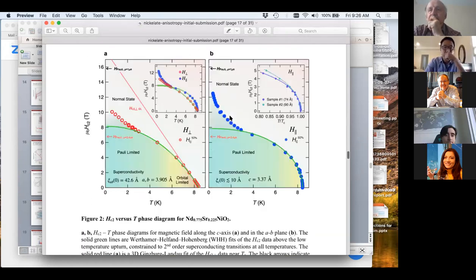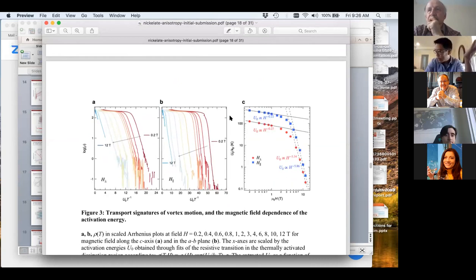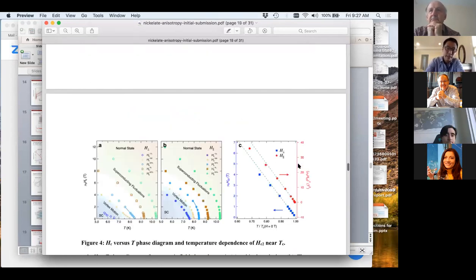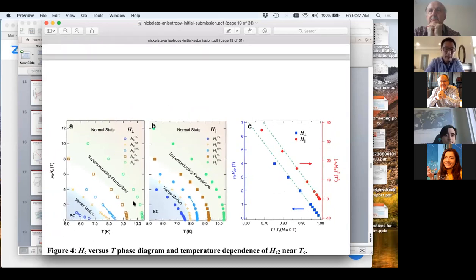The second thing we see is what looks, just following classic work by Tom Palstra and these sorts of people, like vortex motion and a flux flow regime. We again see very similar things to what is seen in cuprates in terms of having an activated dissipative transport associated with vortex motion. So to get back to your question, at least phenomenologically, I could say the following. So this percent here means, for example, a 1% resistive transition, so very close to the normal state, 50% or 90%. And then this line here is, for example, using these Aslamazov-Larkin fits or the threshold for where we see vortex-based dissipation. So to make a long story short, I forget the exact numbers, but somewhere between 20% and 80%, if my memory serves, of the resistive transition,